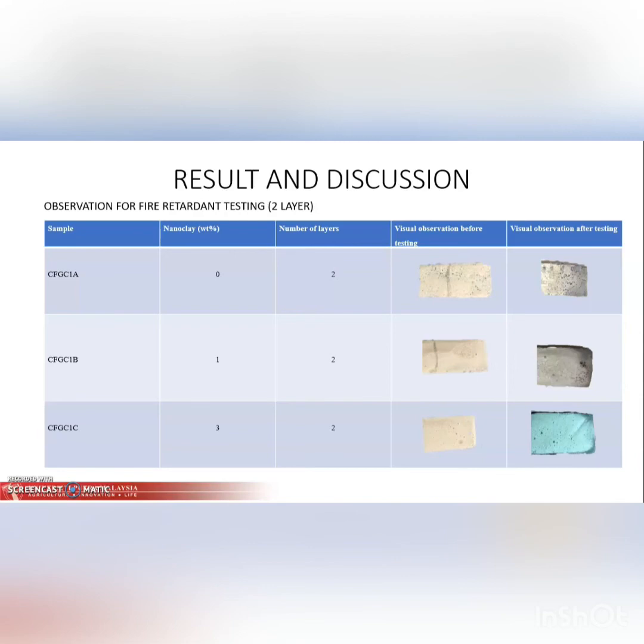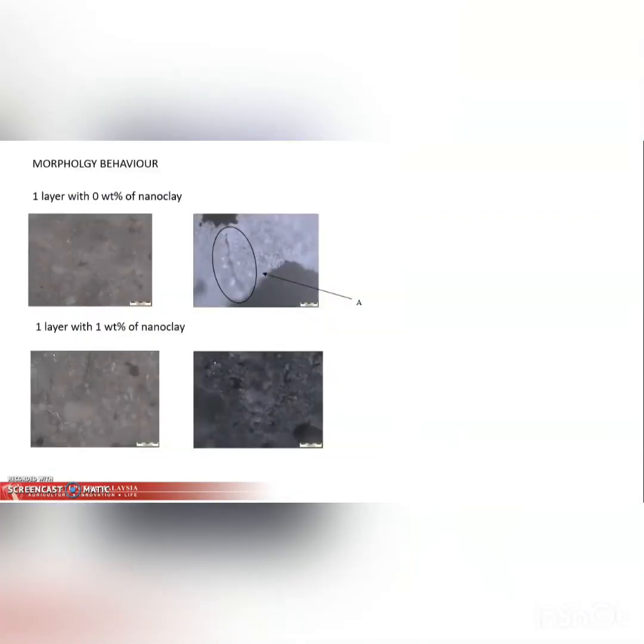Without the addition of nanoclay, the fire from the burner directly reacts with the sample. Therefore, it takes some time for the geopolymer composite with added nanoclay to burn. Apart from that, the carbon fiber has high thermal resistance, where the inclusion of more carbon fiber can reduce heat transfer. It can also be seen here that there is a line of cracking after the testing.